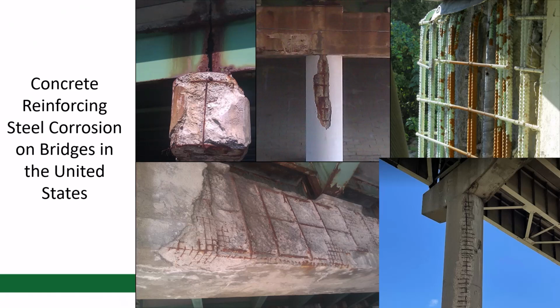The first thing just to talk about, here are pictures from different states. You guys recognize these. Some of these are just corrosion that has occurred because of leaking joints. That's a very common thing. You're going to have corrosion from leaking joints or from snow being pressed up against the side of structures, very commonly. And what we're talking about, just to be clear, is reinforcing steel corrosion. Here's an example of a structure where the DOT actually painted, so they would try to provide a barrier coating, but you see there was some ongoing corrosion underneath the coating. So the coating itself may have helped, but it didn't really solve the underlying corrosion issue, which had already been initiated.